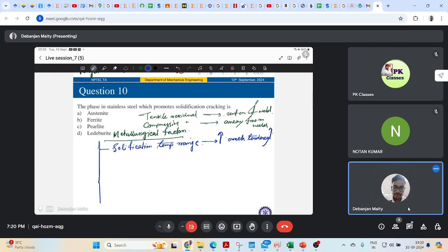They will always increase your solidification temperature range, sulfur and phosphorus in steel, right? Those kinds of impurities always provide severe cracking in carbon steel or low alloy steel, even at low concentrations. They have a strong tendency to segregate at grain boundaries and to form low melting point compounds, such as iron sulfide and iron phosphide. Those are low melting point compounds that segregate at the grain boundaries, weaken the grains, and have some tendency to crack.